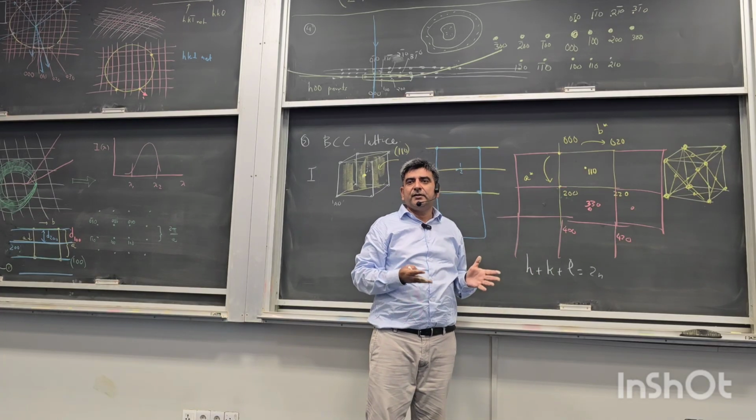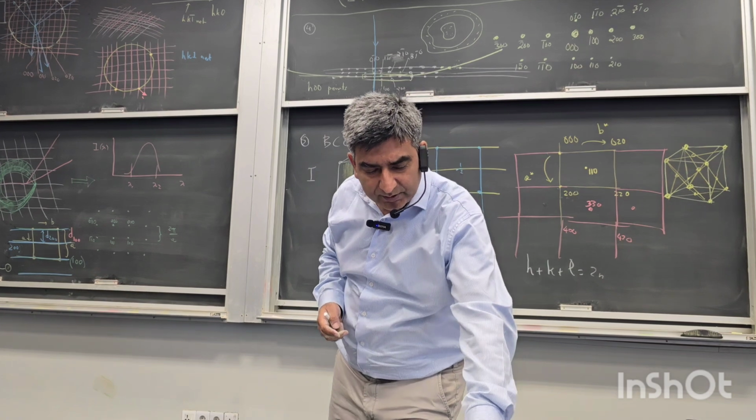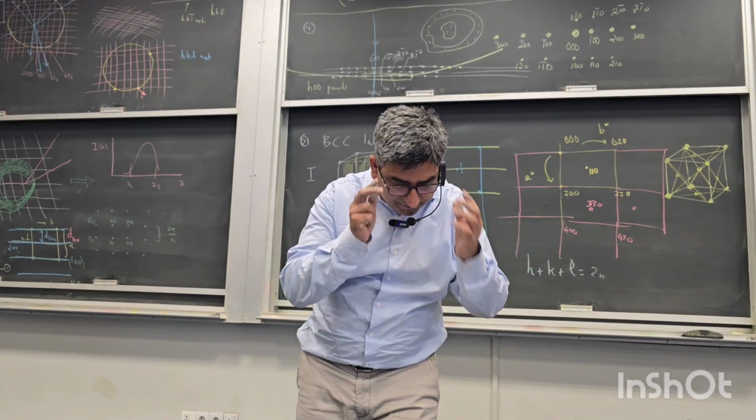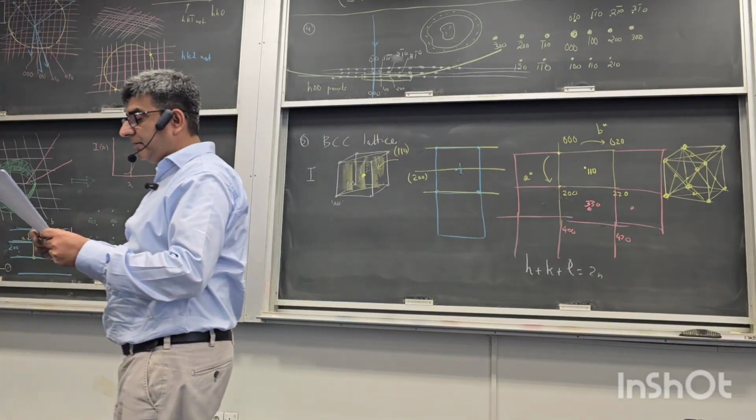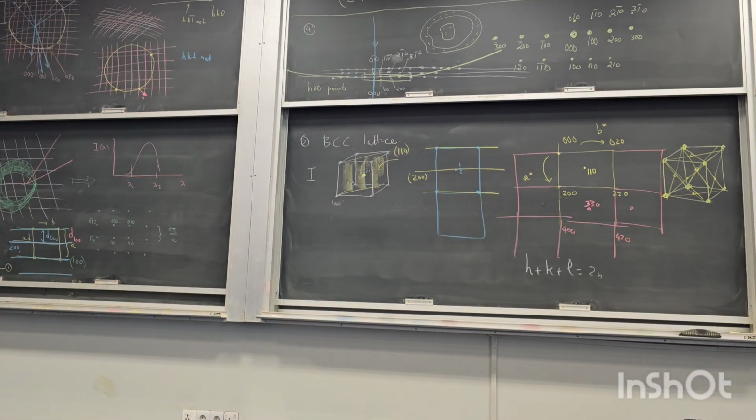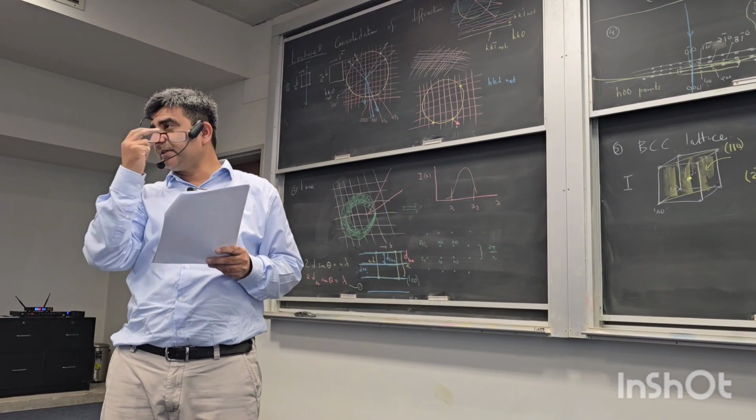See, all of these points qualify for this. And if you look at the space group tables that have been provided, and you look at I m 3 bar m, space group number 229, on the rightmost there is a column that says diffraction conditions. Reflection condition is the rightmost column, and for I m 3 bar m, which is of course body centered, for general points the condition for reflection is h plus k plus l is 2n.